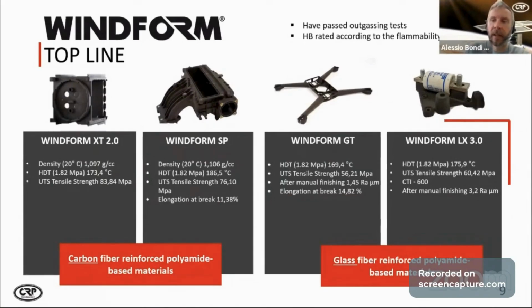As part of the family is the electrical insulated material, Windform LX 3.0, which has a CTI of 600 and very good HDT as well, 175, and acceptable UTS, 60 megapascal, and also good manual and good surface finishing. So the first 2 are, as you can see, carbon fiber reinforced, and the second 2 are glass fiber reinforced.